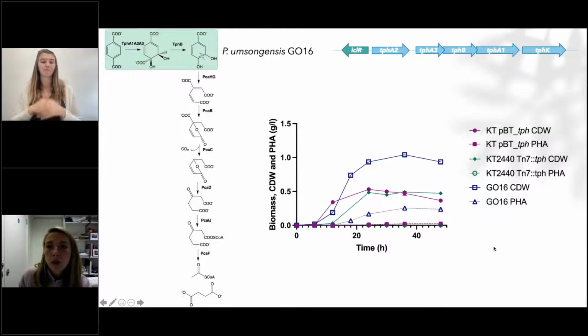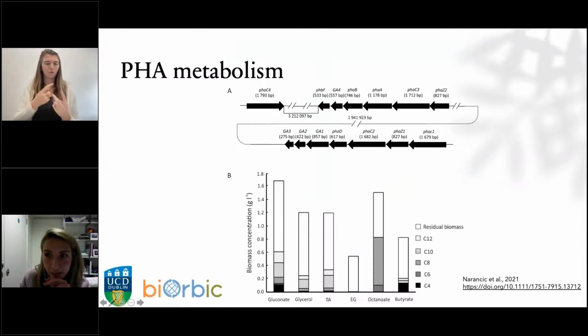So we then started looking more closely into the metabolism of GO16, and we have noticed that GO16 has essentially two sets of pathways for the metabolism of protocatechuate, and we're now trying to learn more to better tune this part of the pathway and improve terephthalic acid metabolism in GO16, thereby removing certain obstacles that exist in terephthalic acid metabolism. And we're also learning from that and trying to improve metabolism of terephthalic acid in KT2440. Because I don't have too much time to talk about this, if anyone is interested in why we would have two Pseudomonas strains now growing with terephthalic acid, I'd be happy to discuss that with you later.